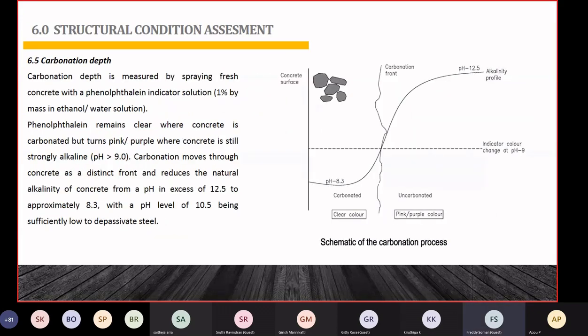Now the carbonation depth, same like the chloride content. Carbonation depth is also very important. Same, from the surface, up to what depth it is carbonated. That's important, because up to that depth the concrete has to be removed, and we want to replace it with new concrete or new repair material. Okay. Carbonation is also very important. That's why we do the carbonation depth test. Okay, sir. Moving to the next slide.